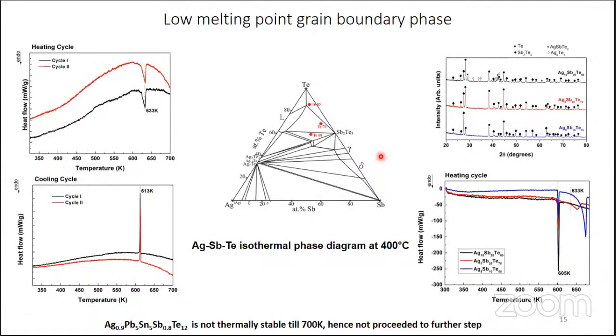Then this is a bit of metallurgy, and we analyzed it thoroughly. When we did, we found that these secondary phases can melt and form a low-temperature melting alloy. It can even melt close to 600 Kelvin, and that is what our TG and DSC analysis showed. So if there is a small amount of secondary phase that melts at 600 Kelvin, then in spite of the material showing a very high ZT at high temperature, certainly it cannot be used for that high-ZT application. The temperature where the ZT shows its maximum, until that temperature we cannot use it. So that's the point here.